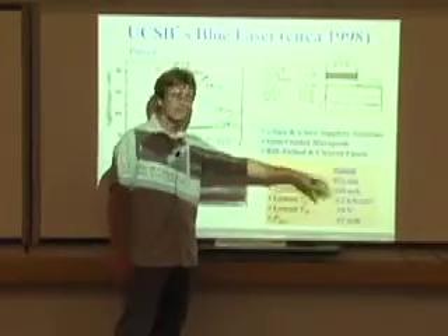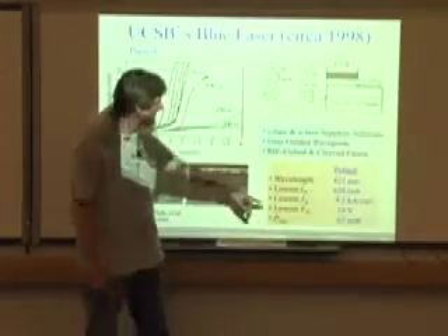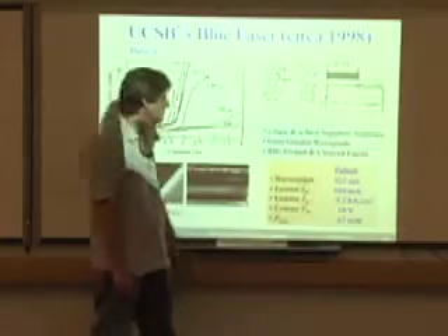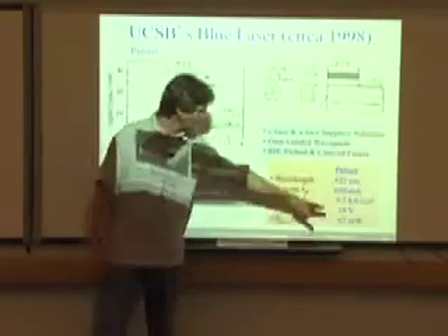And here, at 420 nanometers, 650 milliamps was the lowest threshold they were able to get to at the time. 19 volt thresholds, again, very similar to everybody else. But nice output power, 67 milliwatts was the max at the time. And Sony, very similar story.